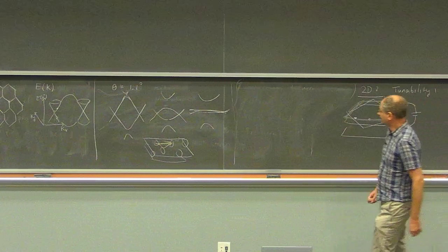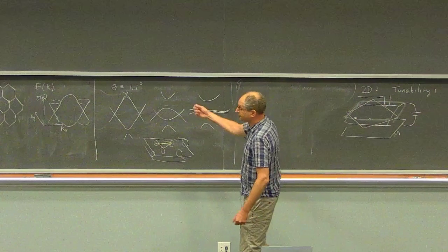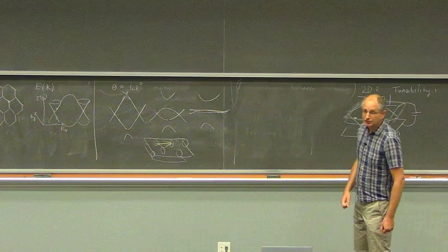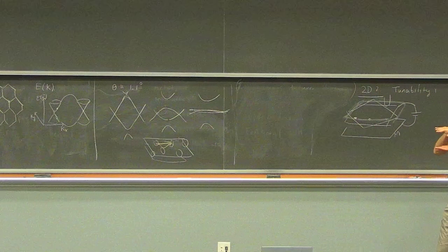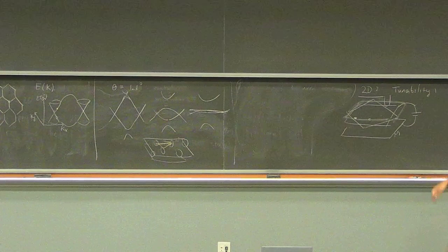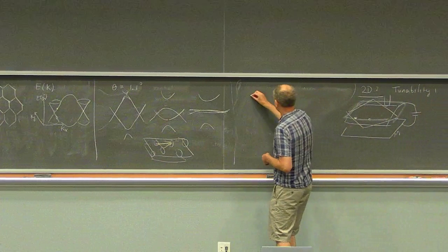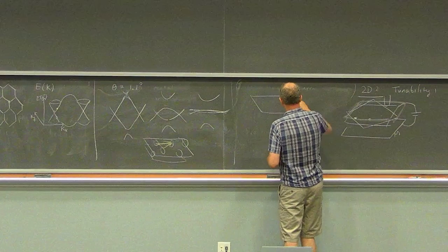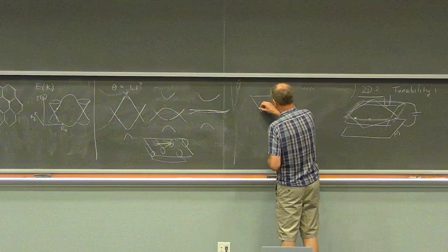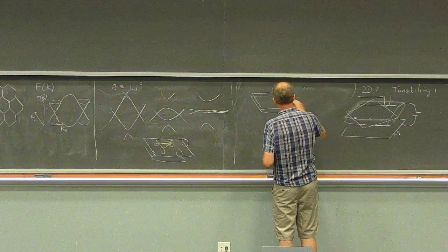Right, so it turns out that much of the same physics you can access just by stacking graphene sheets on top of each other, without twisting. Okay, so now no twist, especially if you do it with more than two layers, even though much of the physics appears already at 2 layers.